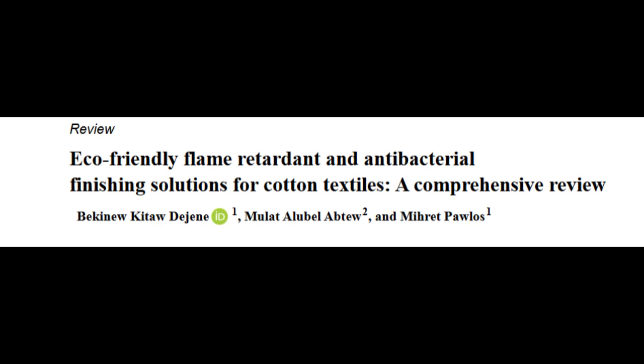How well does it work? Pretty well. Studies show it can give cotton a really high LOI. And importantly, it seems quite durable. One study found it kept a good LOI even after 50 washes. 50 washes? That's crucial for clothing. How does it stick? It seems to form strong chemical bonds, covalent bonds, with the cotton fibers. And its mechanism is mostly in the solid phase, promoting that char. Okay. What about the others?